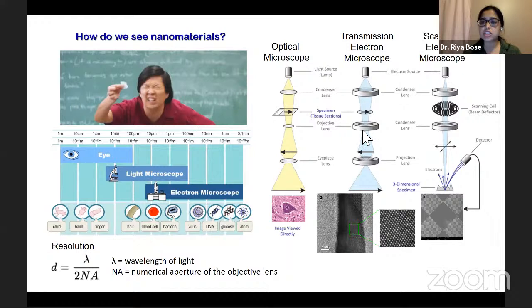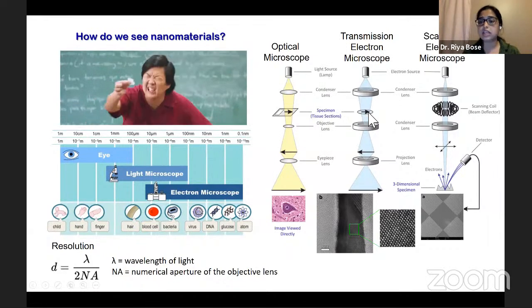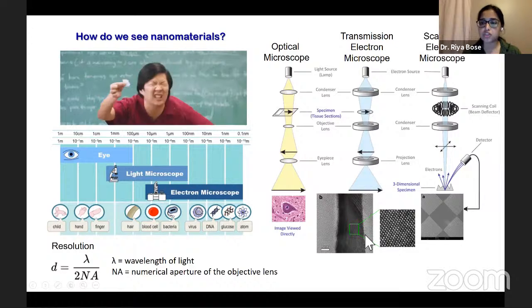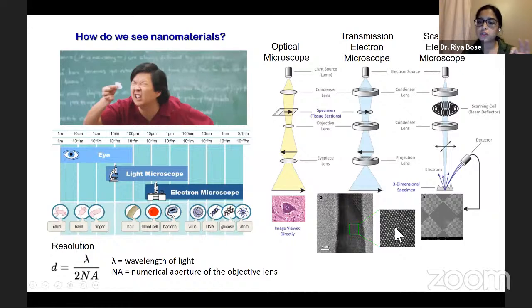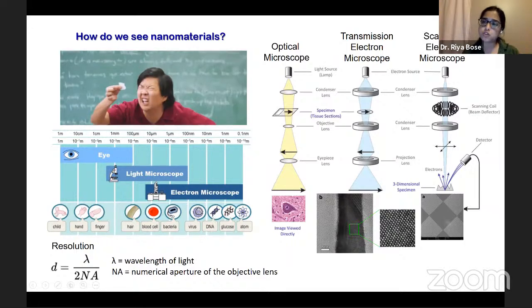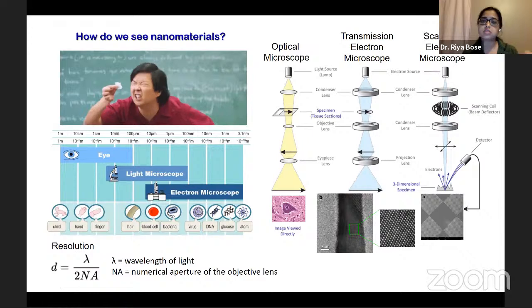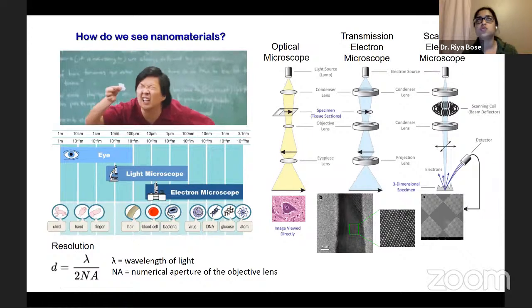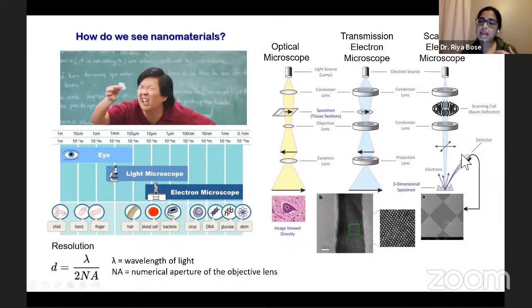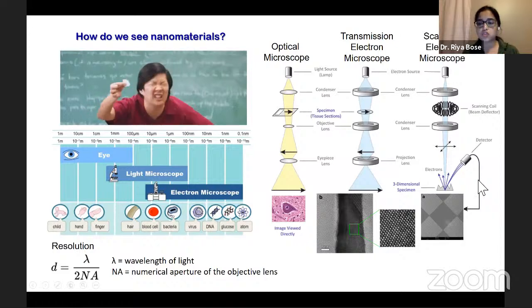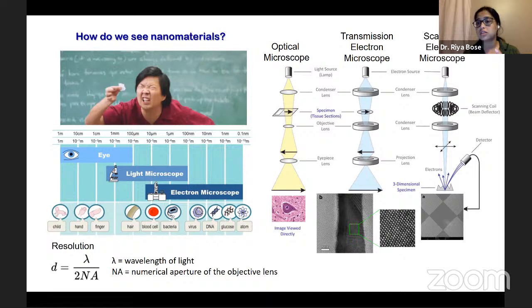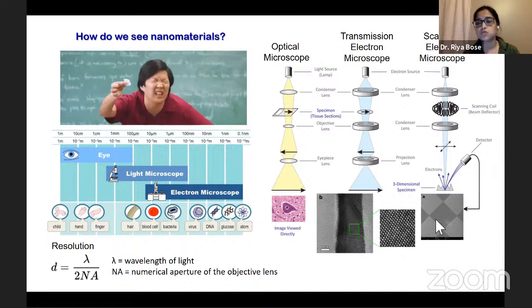In a transmission electron microscope, the sample is placed in the path of the electron beam. So the electron beam goes through the sample, which helps in getting a much better resolution. If you see this image, the small dots are actually atoms of this material. So you can see individual atoms, and with the latest transmission electron microscope, you can go to a resolution as low as picometers. Whereas a scanning electron microscope scans the surface of the sample, and the scattered electrons are detected by a detector, which forms an image. It does not have a resolution as good as the transmission electron microscope, and it is mostly used to know the surface morphology.